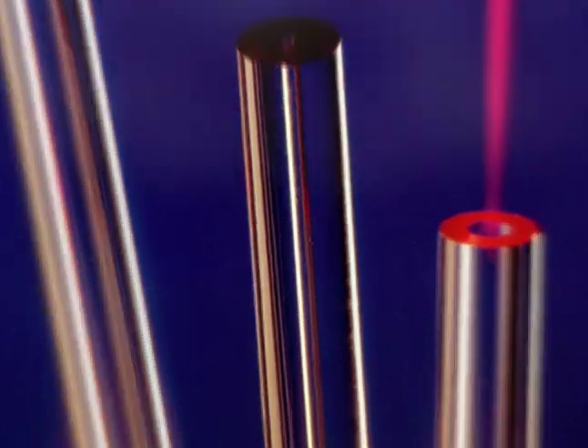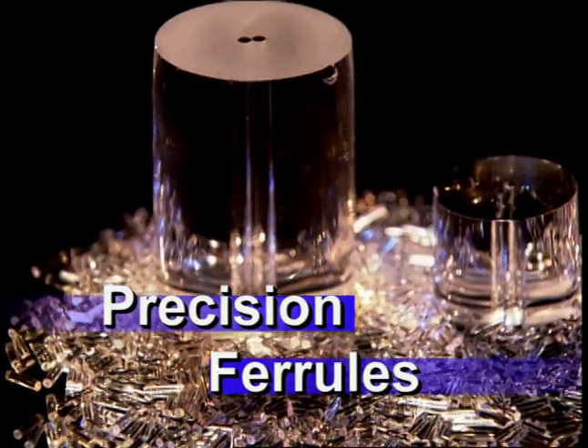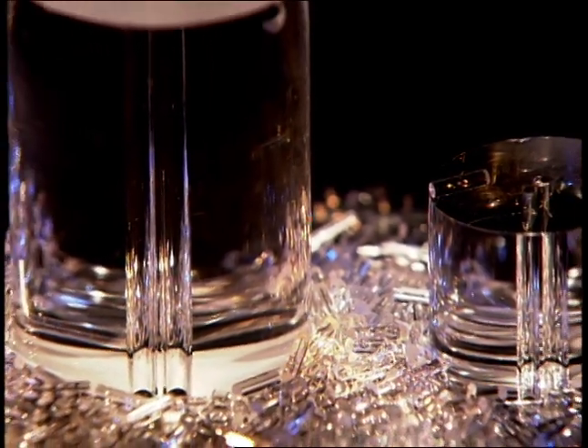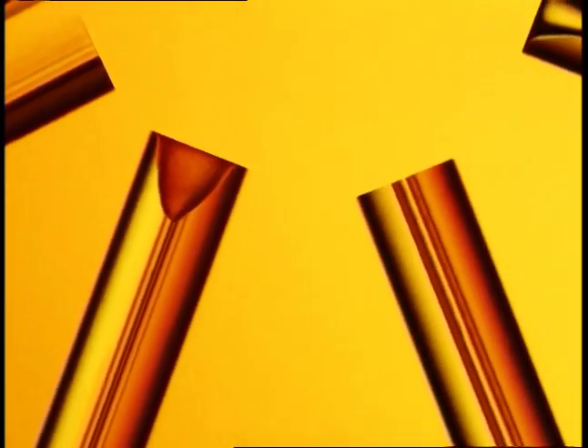Larger diameter products are rigid, uncoated, and can be made with either synthetic fused silica or natural fused quartz. In addition to optical fiber and capillary, Poly Micro offers precision quartz ferrules and ferrule sleeves for fiber or capillary terminations. The quartz material closely matches fiber properties of thermal expansion and hardness, thereby providing higher strength and purity with resistance to splitting, chipping, and cracking. The ferrules can be custom designed with unique geometric profiles; internal and external geometries can be combinations of round, rectangular, and square, as well as other shapes.